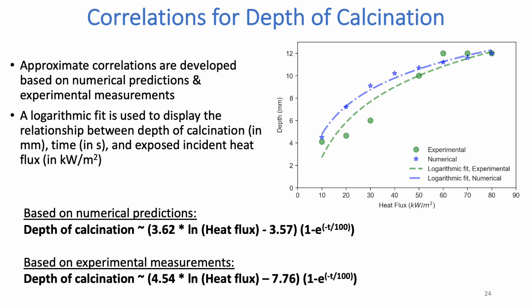And we developed correlations, and the second part of that correlation, that's 1 minus e power minus t by 100, is a correction factor if the exposed duration is very small. If the exposed duration is more than 8 minutes, that part goes to near unity, and when the duration of exposure is very small, this entire equation is needed.